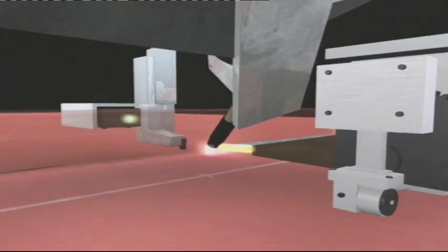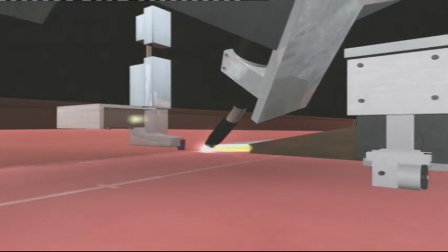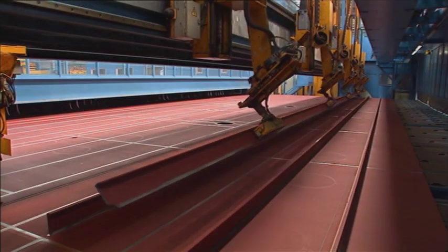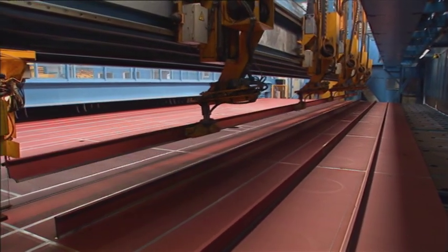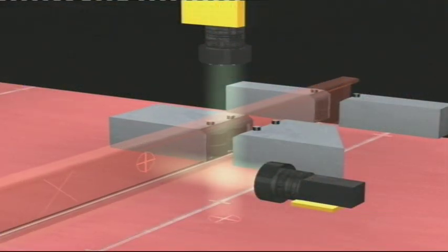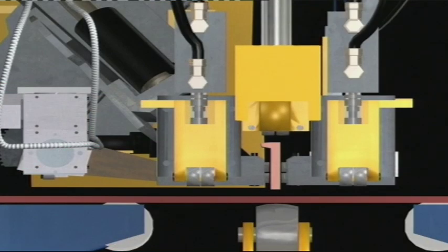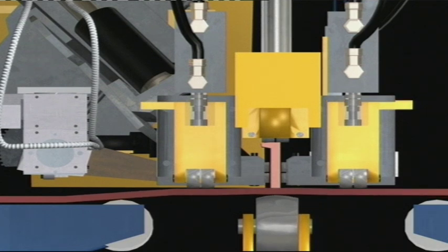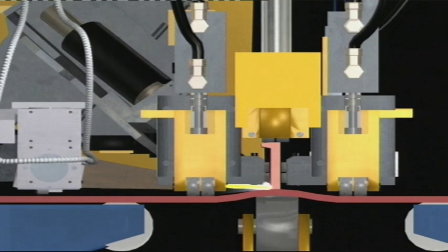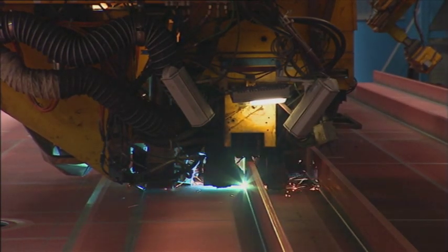The plates are aligned before laser hybrid welding begins via horizontal and vertical cameras integrated into the welding head. The profiles are mounted onto the previously marked areas of the panels. After they are clamped laterally, the profile is tensioned using a clamp shoe and a pressure roller. The blank holders overbend the sheet metal. During the welding process, a vertical camera monitors the positioning line to align the profiles.